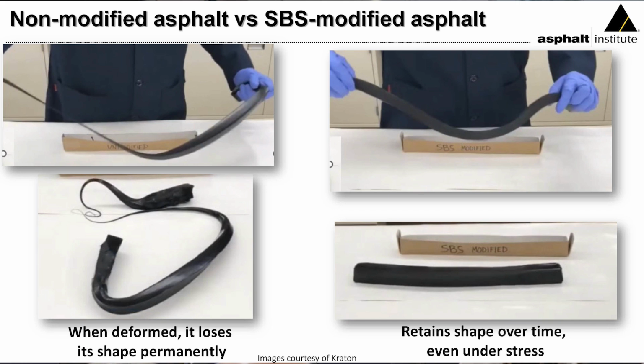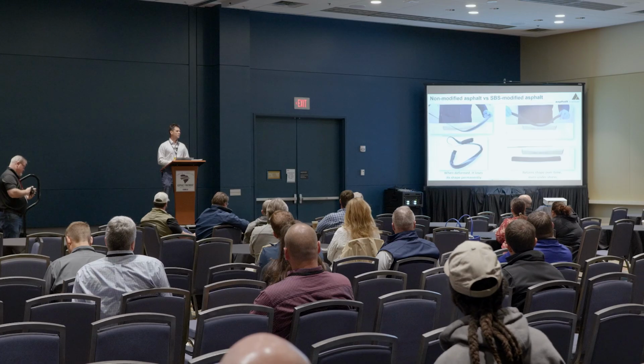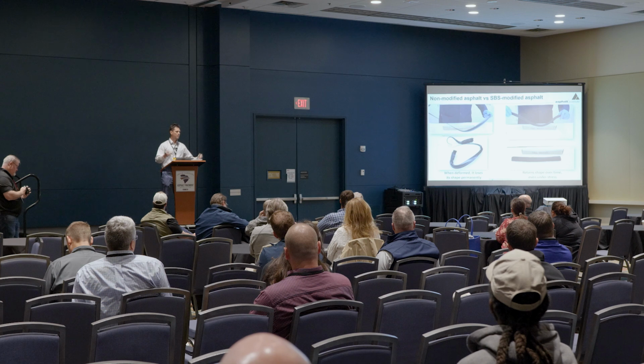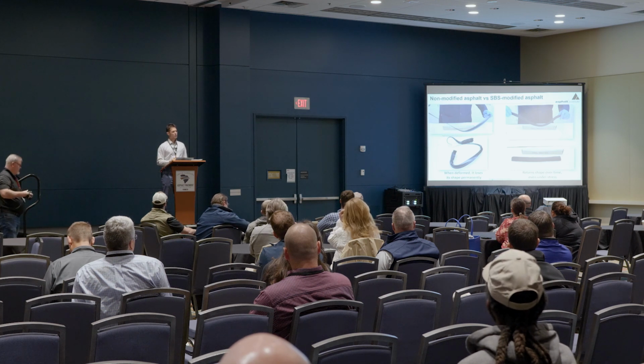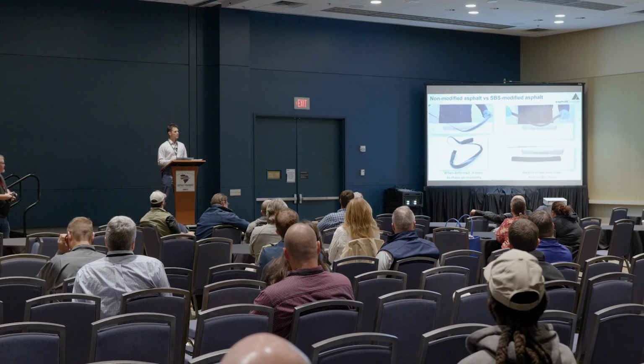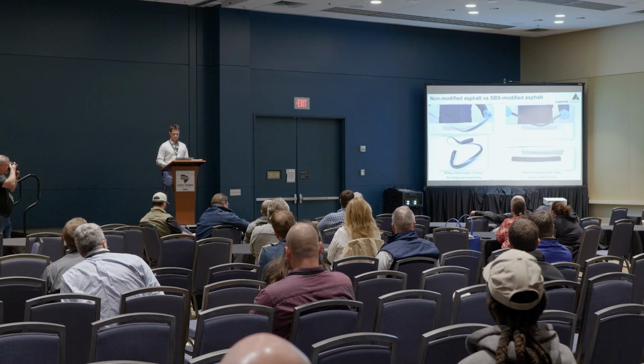So this is kind of a demonstration that's done to show what I'm trying to communicate about the ability of the binder to return to its original form. So if you stretch out a binder that contains no polymer modification, it's not likely to return at all to its original form. It's going to stay deformed after it's separated. However, if you take a specimen that's been modified with polymer, it's very likely to return very close to its original condition.